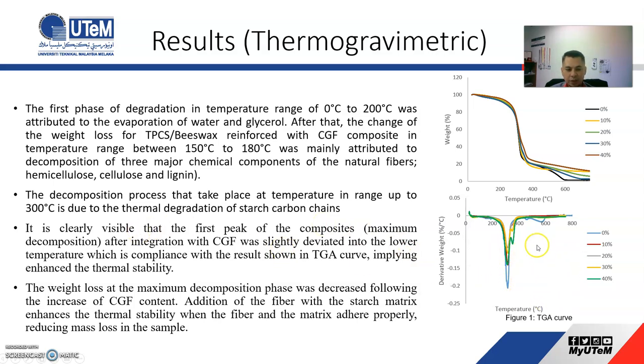Okay? So basically, if you see these figures, this is the DTG figures, it is clearly visible that the first peak of the composites after its maximum decomposition, after integration with CGF, was slightly deviated to the lower temperature. As you can see, it's slightly shifted to low temperature, and then this peak is reducing. The intensity was reduced from the 0%. This peak is reduced to the lower derivative rates, which means that the maximum decomposition was decreased following the increase of CGF content. This is because this decomposition was mainly attributed to the starch decomposition. Okay, so addition of fiber enhances the thermal stability, and the fiber matrix adheres properly, reducing mass loss in the sample.